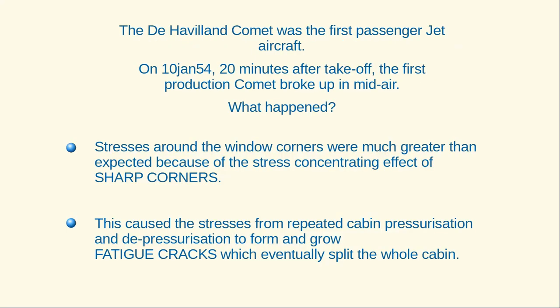The de Havilland Comet was the first passenger jet aircraft. On the 10th of January 1954, 20 minutes after takeoff, the first production Comet broke up in midair. What happened? Stresses around the window corners were much greater than expected because of the stress concentrating effect of sharp corners. This caused stresses from repeated cabin pressurization and depressurization to form and grow fatigue cracks, which eventually split the whole cabin.